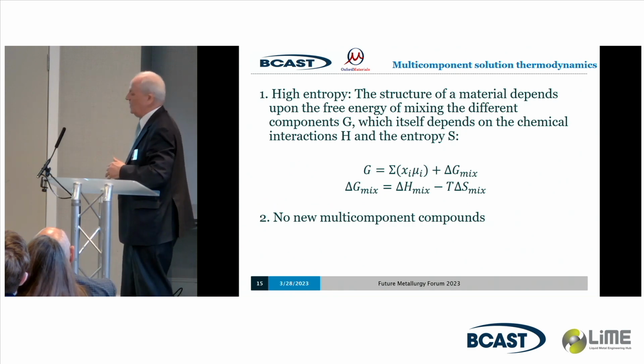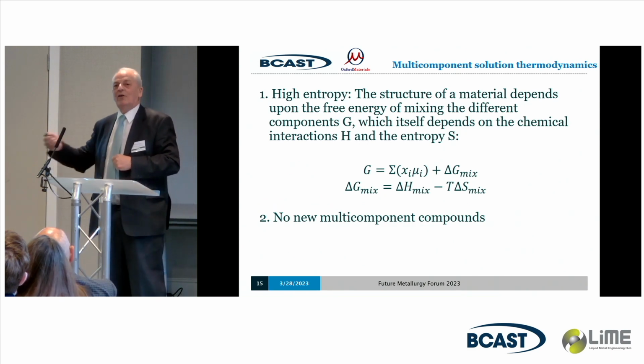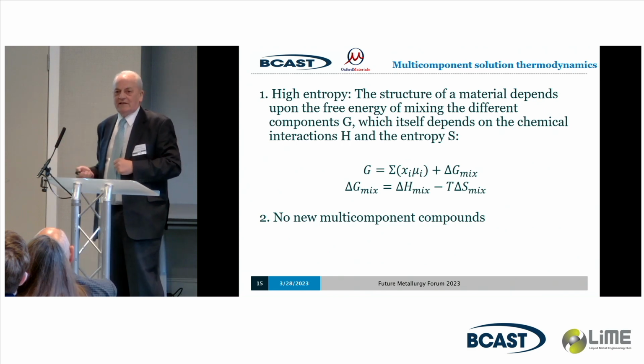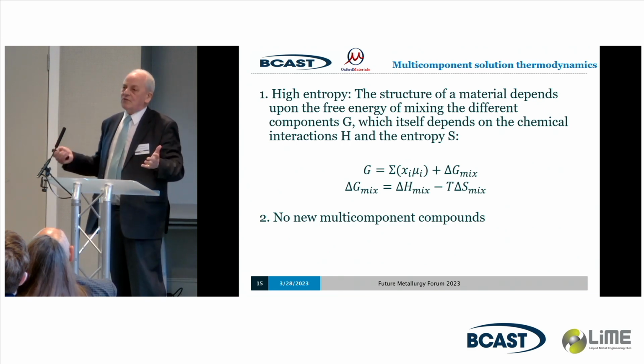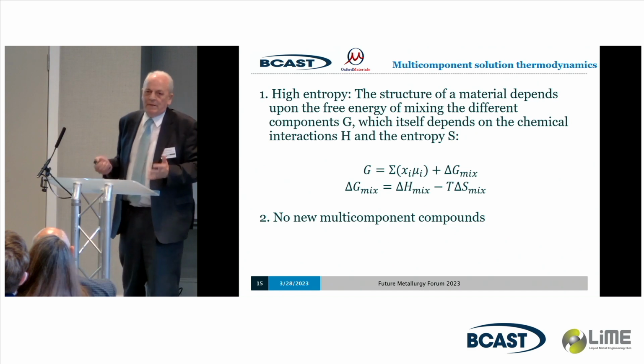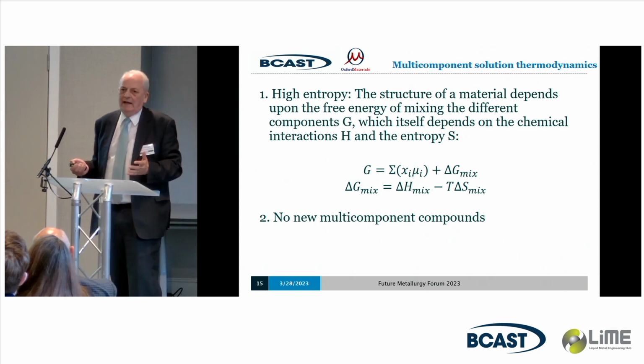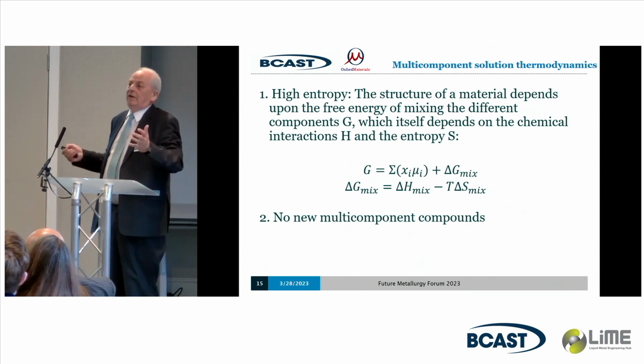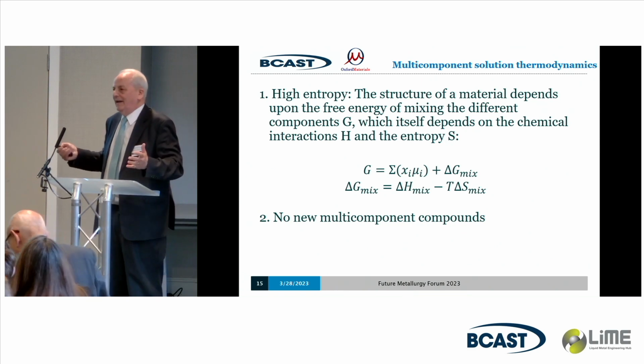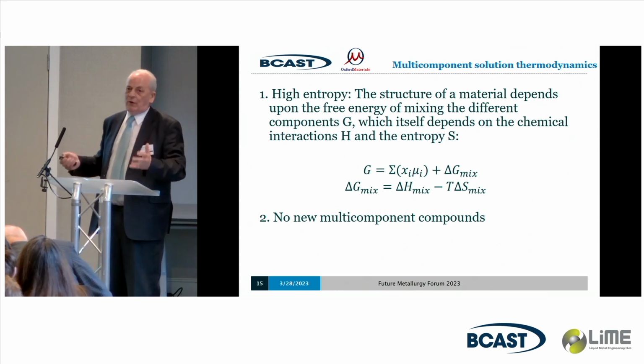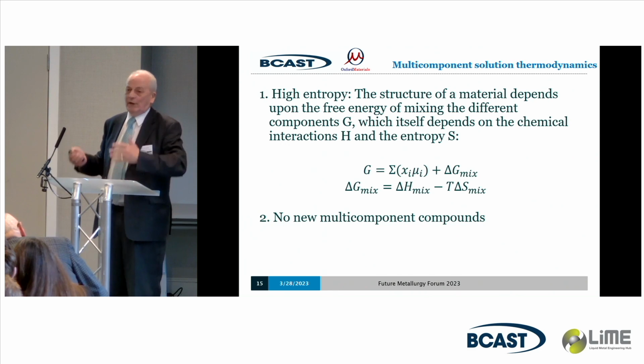But if you add enough, you go over the hump and you start to suppress the compound formation because there's an entropy term, and if you add enough material, then on a single phase, you get the entropy suppression. So that's why Jien-Wei Yeh, who also independently discovered this whole idea, called them high entropy alloys. Brilliant name, brilliant idea. But it's wrong. Lots of multi-component alloys are not high entropy, but lots of them are.